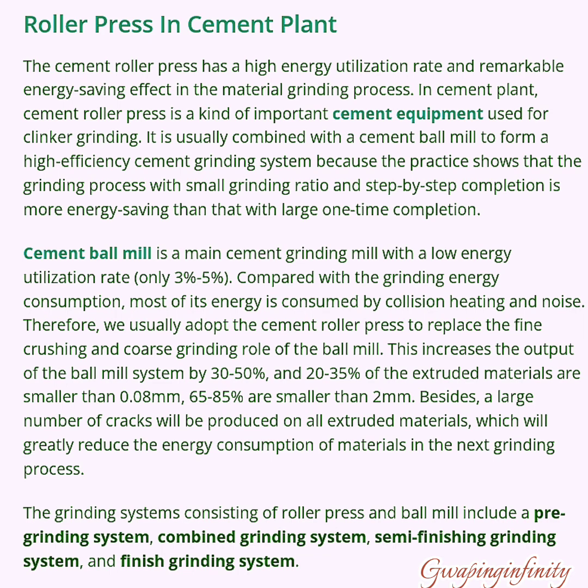This increases the output of the ball mill system by 30 to 50%, and 20 to 35% of the extruded materials are smaller than 0.08mm. 65 to 85% are smaller than 2mm. Besides, a large number of cracks will be produced on all extruded materials, greatly reducing the energy consumption of materials.